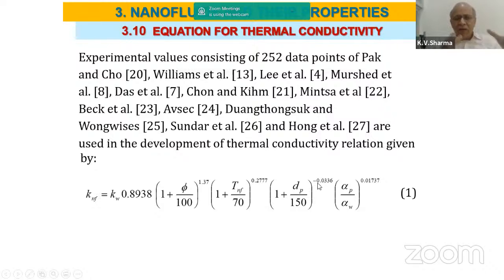So we can understand the physics of the problem by looking at the constants that we have developed. And if the thermal diffusivity of the particle, all of you are aware that thermal diffusivity is k by rho Cp, of the particle to that of the base liquid water, as this value increases, the thermal conductivity increases. This increases for metals, so for metals it will be higher. For oxides, it will be lower. So that also is getting reflected. So this equation can be used to determine the thermal conductivity of a nanofluid.